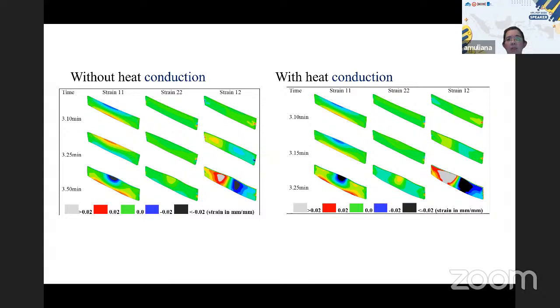So now the lesson that we could take from here: we see the significant thermomechanical coupling, right? At one time, the mechanical response of the polymer is very sensitive to temperature change. And on the other hand, when this polymer undergoes microstructural changes and is also viscoelastic, it dissipates energy, where if we keep on cycling this material, it generates heat, which in turn changes the properties of the material. So this is what we call the coupling phenomena, right? So eventually, even though you think I did not apply any temperature, the material would generate heat, and it would eventually lead to structural failure. So this is an example of how we simulate or model a thermomechanical coupling problem.